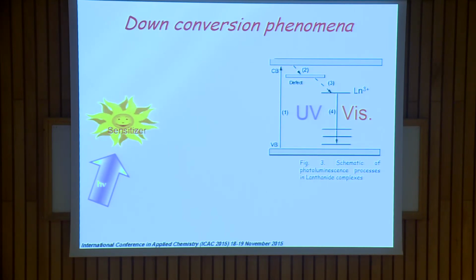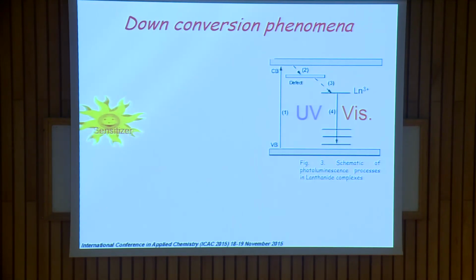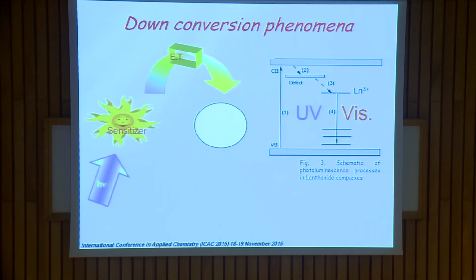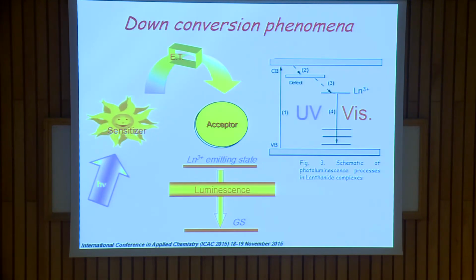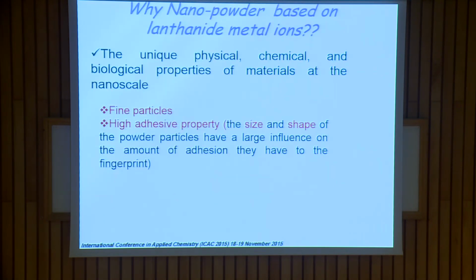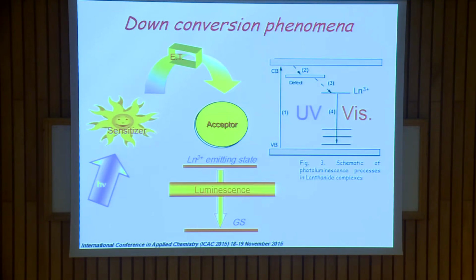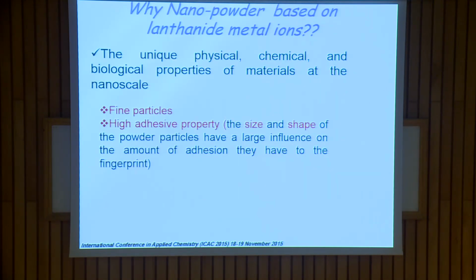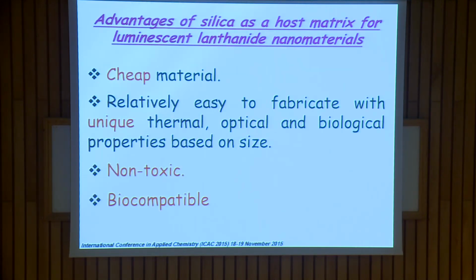This matrix is excited by UV or blue light, and then transfers its energy into the emitting state of the lanthanide. As a consequence, the lanthanide gives the characteristic emission in the visible region, depending on the doping metal ion. This phenomenon is called down conversion, which absorbs high energy and converts it into visible light. Why nanopowder based on lanthanide? Because the fine powder gives high adhesion to the surface.